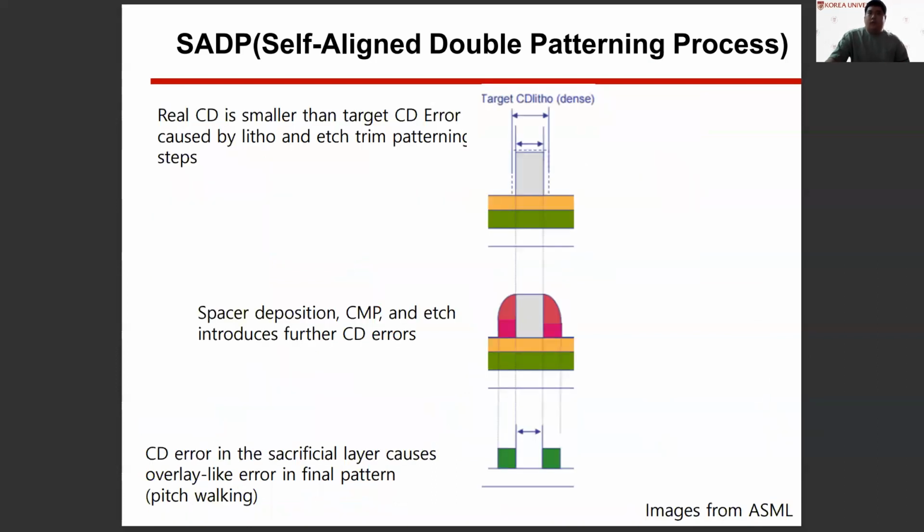Even though this process is easier than the LELE technology, while we remove the mandrel, the spacer or the hard mask itself can be slightly destroyed. They make an overlay-like error, and this is called the pitch walking error.